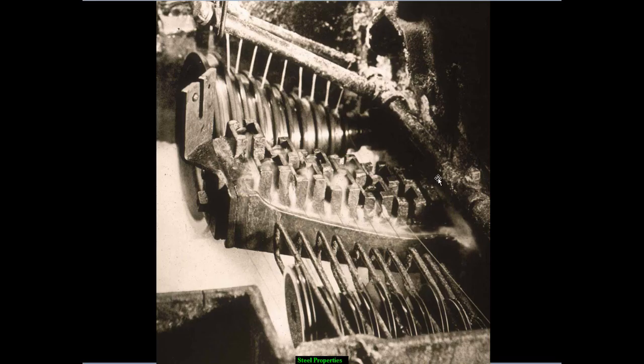This is kind of an old picture, and I apologize for it, but there's a series of rollers here, and the wire is going back and forth and being drawn through dies as it's proceeding. This stuff right here is just a sort of liquid which is poured over this whole process to cool it down. But basically we have a continuous piece of wire going through here, getting smaller and smaller at each point, and at every one of these stages there's friction on it that's pulling it in this process. So we can start with a rod that might be a half inch in diameter, and by the time we get done we might reduce it to an eighth of an inch or less. And it starts off as fairly mild steel that can tolerate maybe 36 or 56 kips per square inch of stress before it yields, and it ends up as 250 kips per square inch by the time it's done.